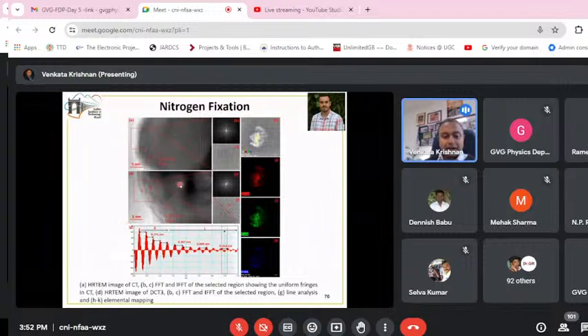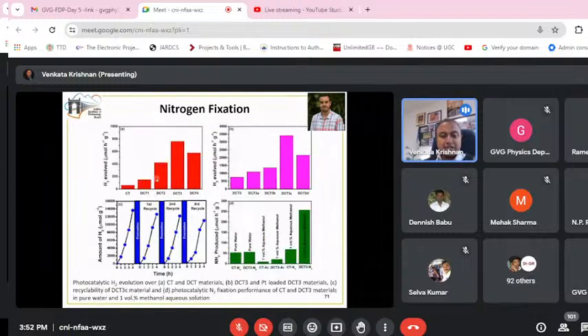We did a detailed HRTEM analysis to understand the vacancy formation and more details about the sample. We first utilized the sample for hydrogen evolution, wherein water was used as the solvent and hydrogen got evolved from the water. Subsequently, we used it for ammonia production, and we got a moderate to decent amount of ammonia using this catalyst.